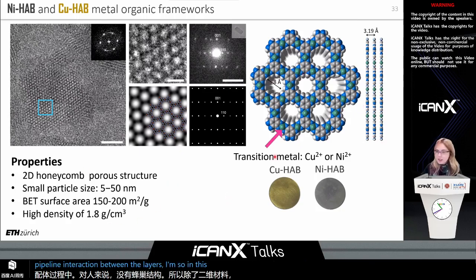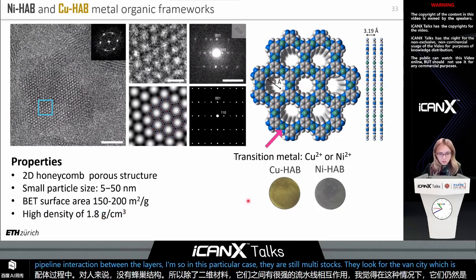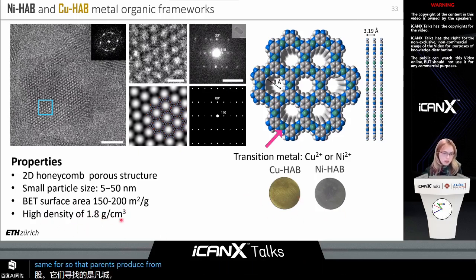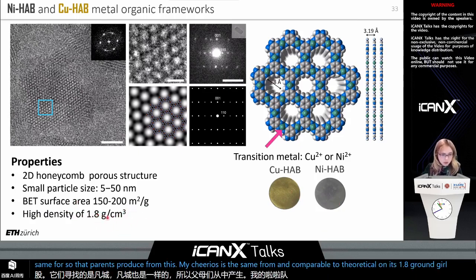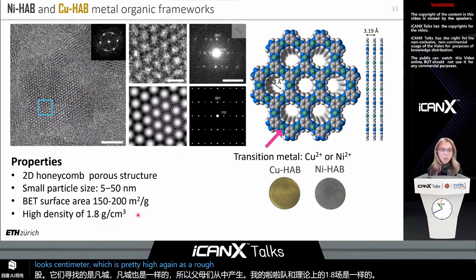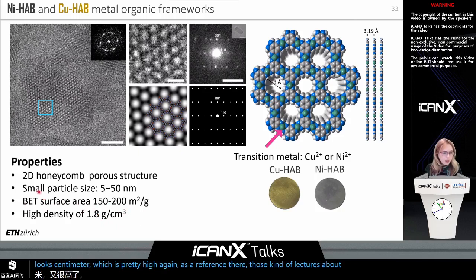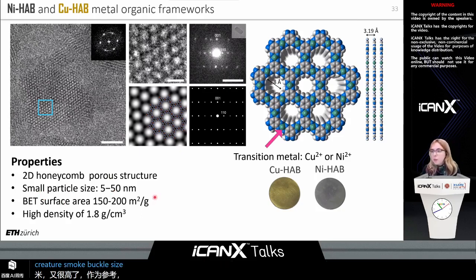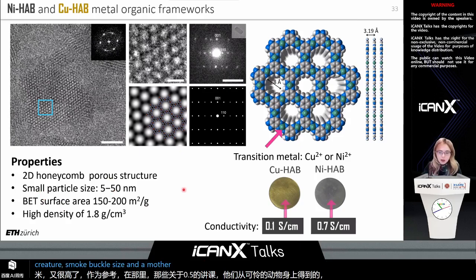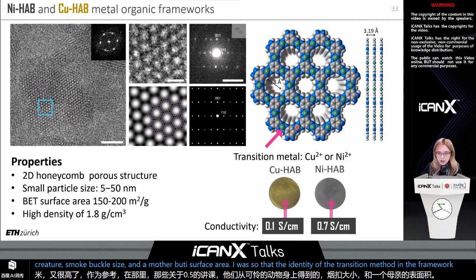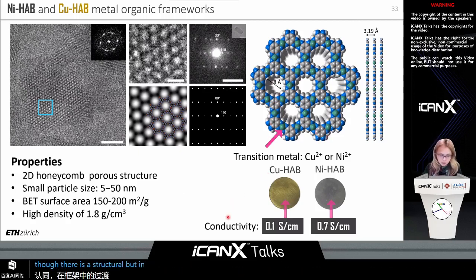So in this particular case, they are still multi-stacks. They offer a density, which for the pellets produced from these materials is comparable to the theoretical one. It's 1.8 grams per cubic centimeter, which is pretty high. Again, as a reference, the porous carbon electrodes are about 0.5. They possess, right out of the pot, pretty small particle size and a moderate BET surface area. Also, the identity of the transition metal in the framework matters: even though they are isostructural, in terms of their electronic properties they are different, even though both are conductive.